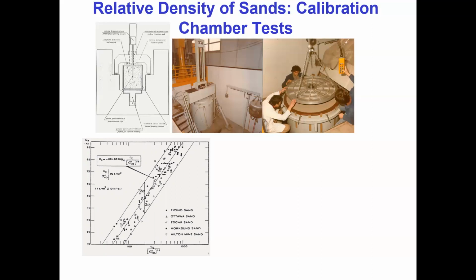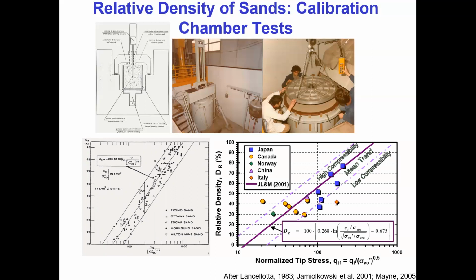And this has all been updated. I'm sure if I asked Paul Mayne to show me this plot, he could show it with a huge amount of data. The story really hasn't changed. What you see in the figure is there is a correlation between the cone resistance and relative density. It's not a very precise correlation. You can see that for a given cone resistance, you're going to be hard pushed to get relative density better than plus or minus 10%, which I think is a useful number. There's a lot of data supporting this.